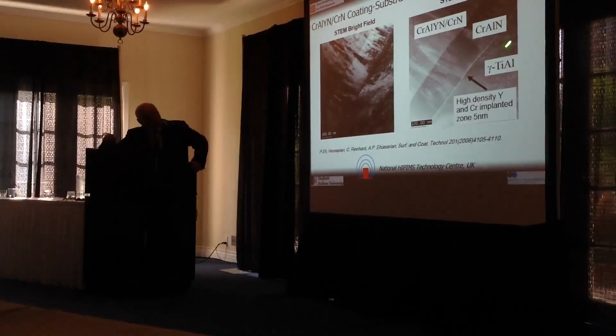And it was not possible to do it by arc because of very huge instabilities if you have it in the target and use arc. But it was very, very easy to do it with HIPIMS. So we have it in the interface with this coating, and we have multi-layers which are based on elements like chromium and aluminum, which produce extremely dense oxide scales. Now, this is how the coating looks like. You have your base layer, the implanted zone, the base layer, and the coating.